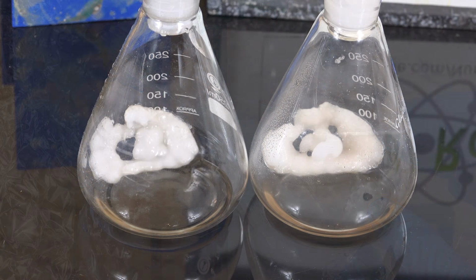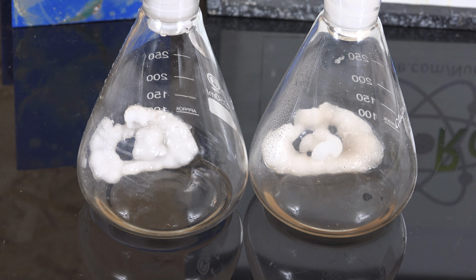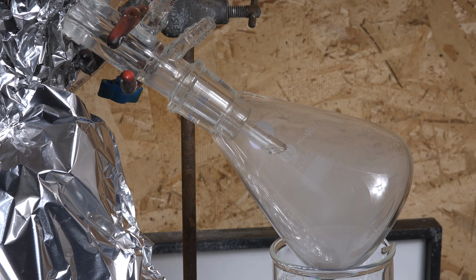So here are the 2 runs of Oleum. They're remaining solid now, so the purity is much higher, and after titration I got somewhere above 80%. The mass collected was about 30 to 35 grams for an effective yield of about 24 to 28 grams of sulfur trioxide, or 20 to 25%. So not quite at my goal of above 30% yet.